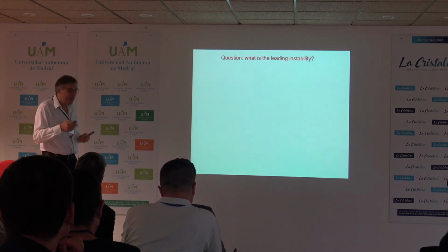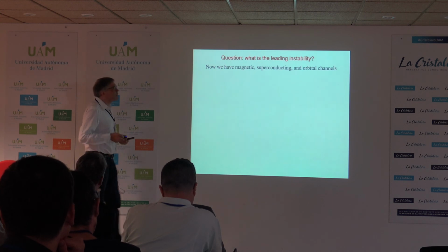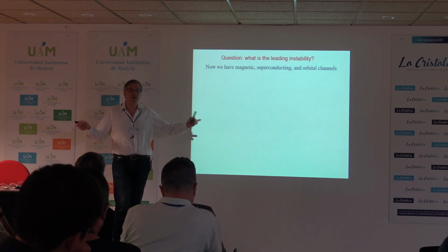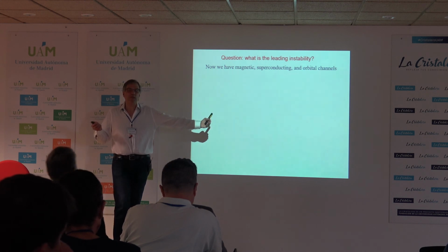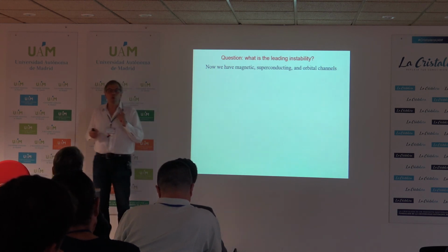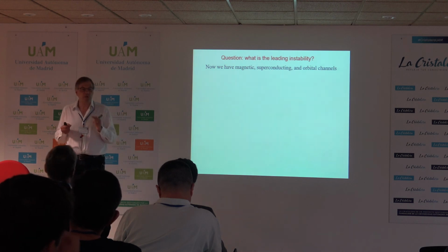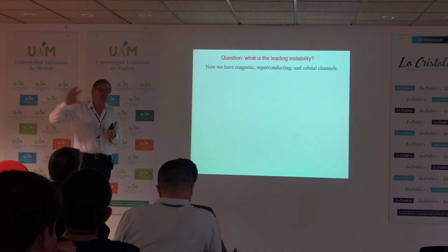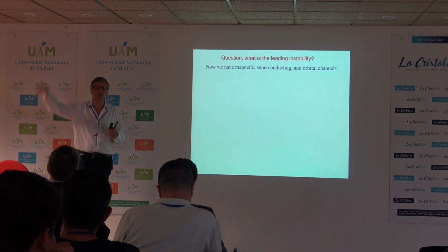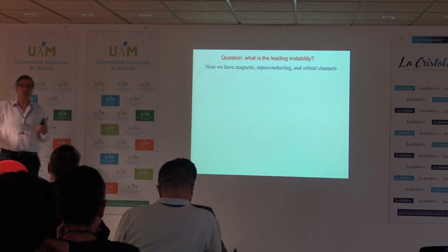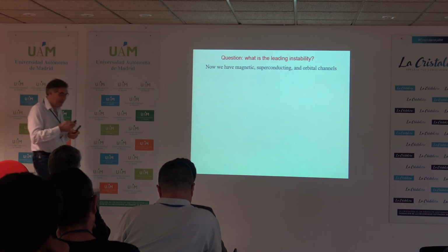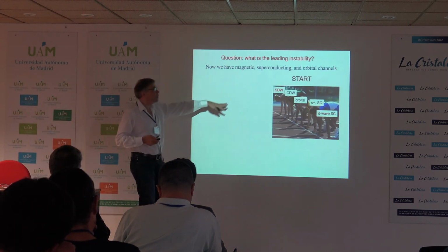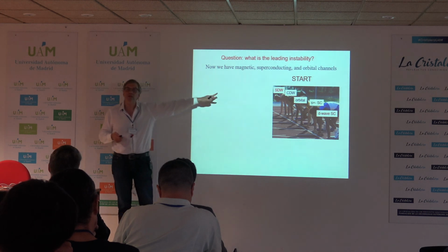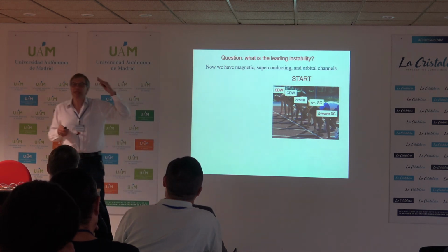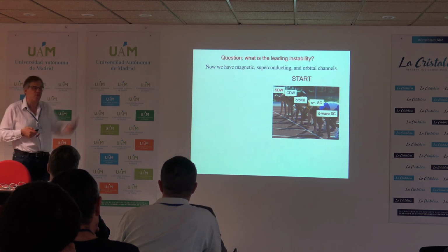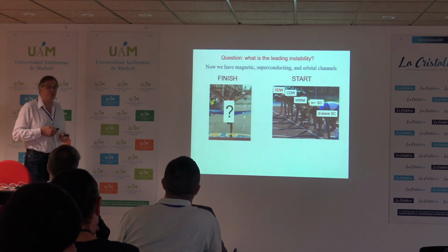So what comes first? And this is where RG is pretty good, because RG treats all channels equally. It doesn't tell you this channel is the dominant one and this is not. Contrary to the effective electron-boson, fermion-boson model, which tells you, let's assume that one interaction is the elephant in the room, either spin density wave or charge density wave, and let's see what the effect of this interaction will be. Here we don't do anything, we just start with all possible candidates. They are all combinations of G1, G2, G4, G44, and then ask which one will finish first.